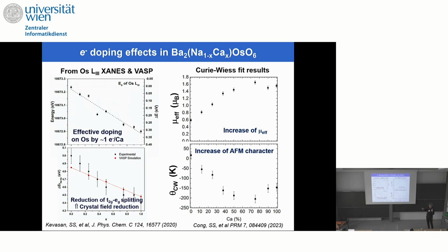And also the Curie-Weiss temperature changes. Here we know that it should be ferromagnetic because of the canting that has been discussed a lot in this conference for the sodium sample. So we expect a slightly positive Curie-Weiss theta. When we increase the doping, we increase the antiferromagnetic character, because theta becomes well negative. Okay, so everything works when we dope the system.